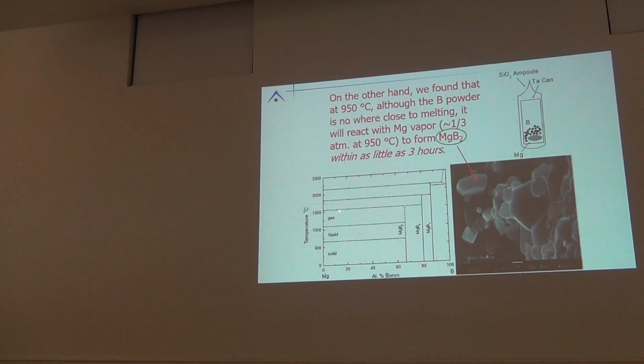On the other hand, you can make polycrystalline samples very easily. And as a physicist, I'll take whatever sample I can measure. I prefer single crystals, but if I can't get that, I'll take high purity polycrystals. You can take high purity boron, magnesium, heat them up, as little as 950 Celsius using this tantalum tubing we developed for other magnesium growths. Okay? And the magnesium vapor diffuses into the boron and you get high purity MgB2. Hooray! And this is much better purity than what you buy from Alpha Aesar or other things. That stuff has lots of oxides and impurities.